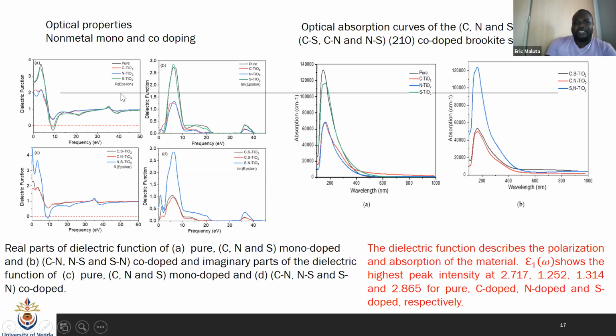On my left, we did also the monodoping and co-doping. And then we have seen that we also change the dielectric constant of the surfaces by putting in more of the foreign elements in the system, because we're just including a defect in a pure system. And this also means that looking at these properties, it gives us a way of thinking that really, if this can be done experimentally, then we will be able to improve the efficiency of the dye-sensitized solar cell.